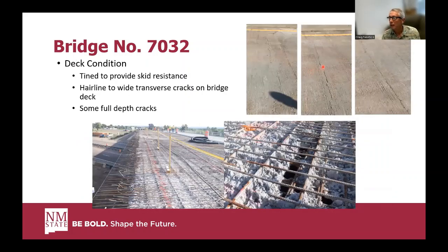So the existing deck, first thing we did was go out and kind of survey that, see what kind of issues they had. There were a lot of transverse cracking, basically thermal cracks in the deck. The deck was tined after construction or during construction. The full depth cracks, you could see them even from inside the multi-cell box girder. And then as part of the project, the contractor was required to perform some hydro demolition to remove the surface material.